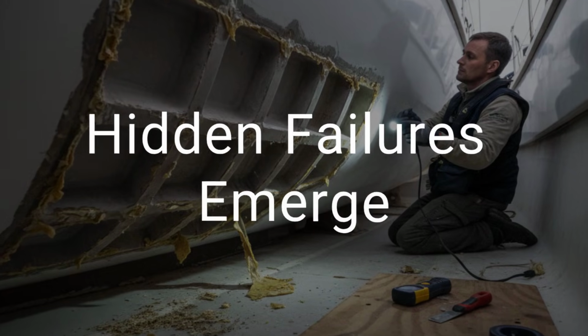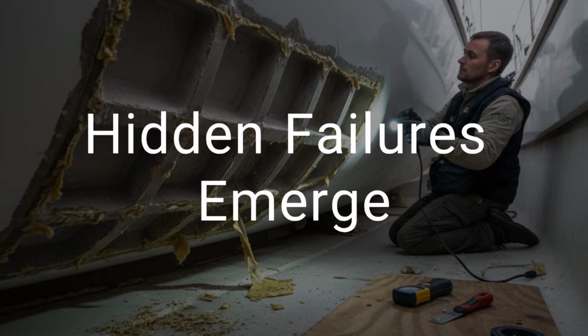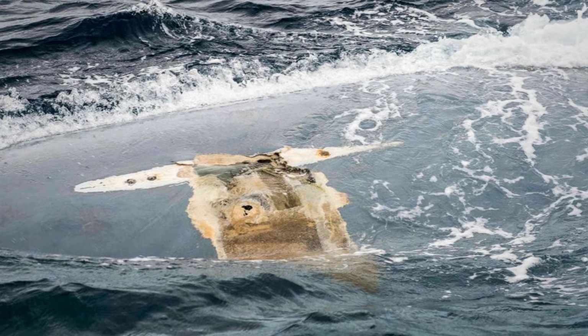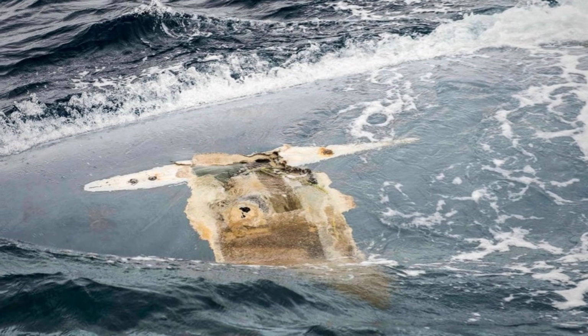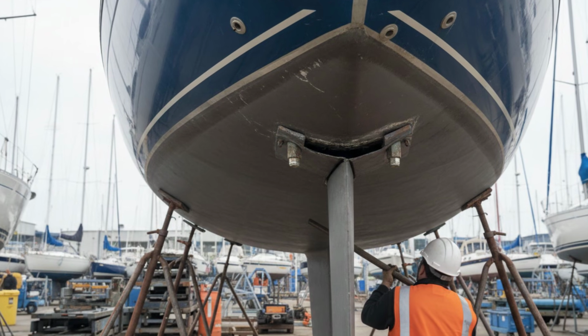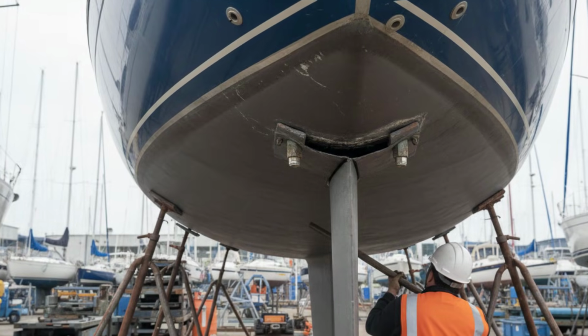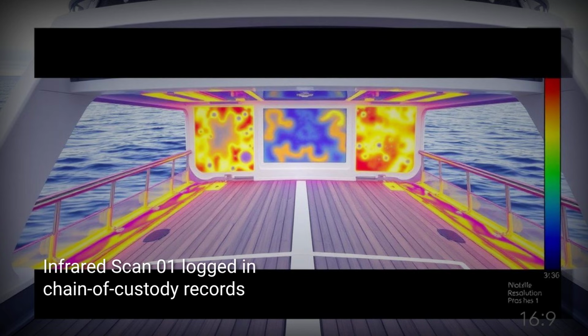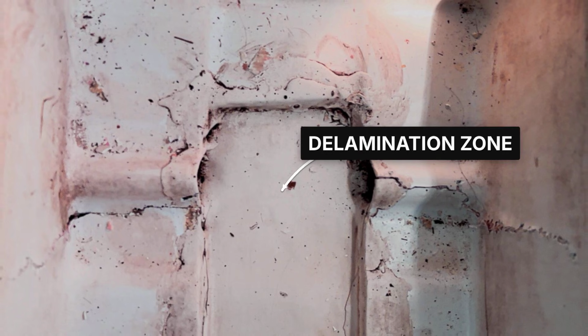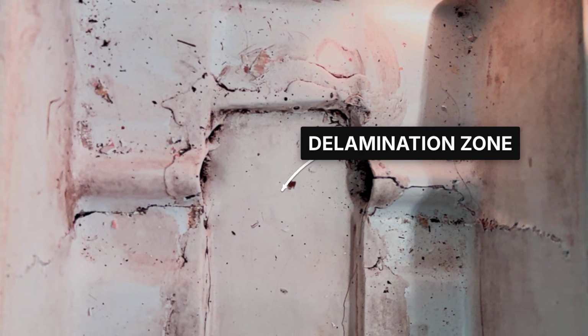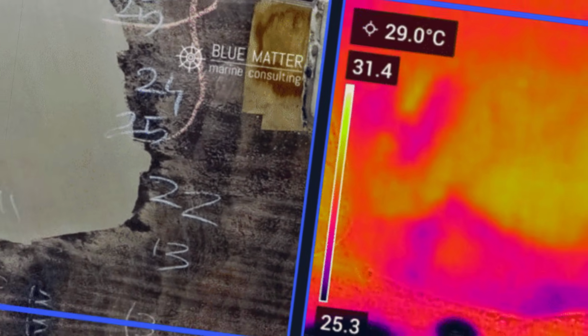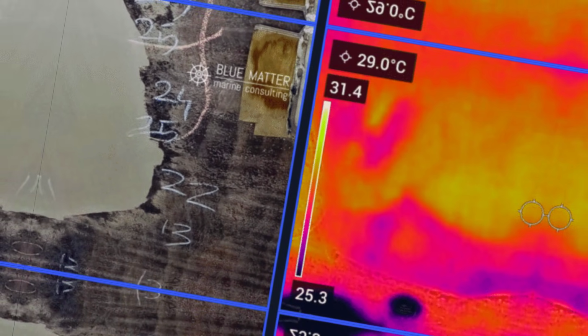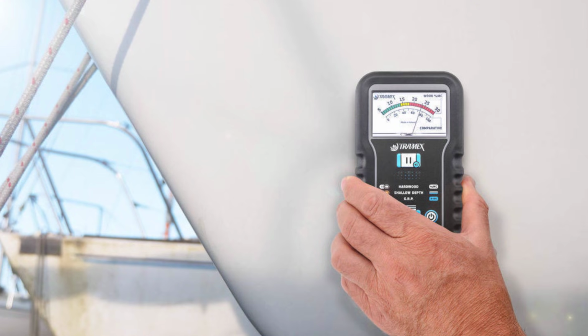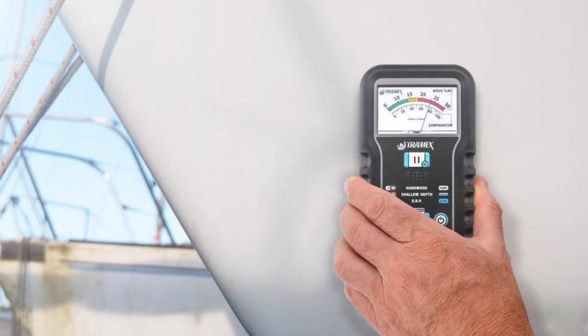Beneath the cabin sole of the Beneteau 46, the evidence is immediate. Torn adhesive traces the outline of a grid that's no longer bonded, while the keel rocks with a looseness that should not exist. Chain of custody logs confirm the surveyor's first infrared thermography scan, a 300mm delamination zone running forward of the mast step along the port grid rib. The infrared images reveal a feverish patchwork, hot spots where the grid has peeled away, cold voids where water has crept between liner and hull.